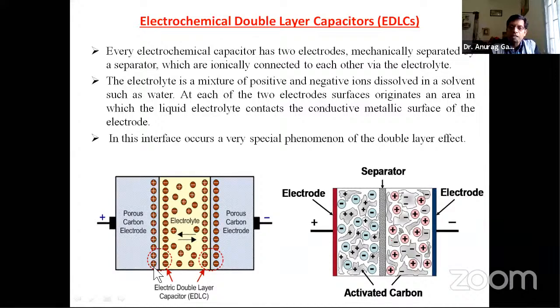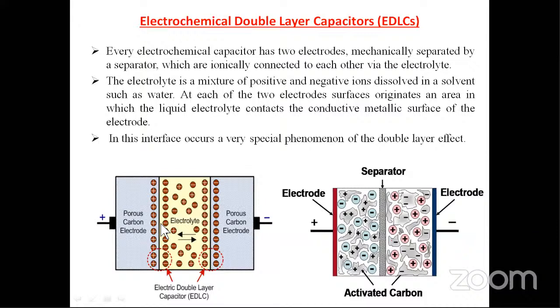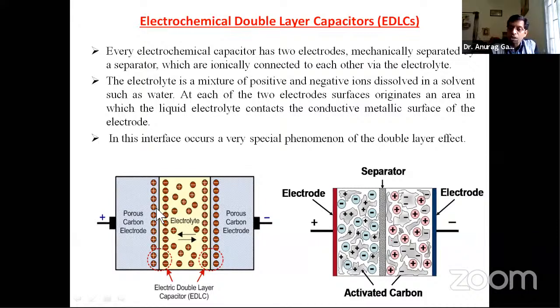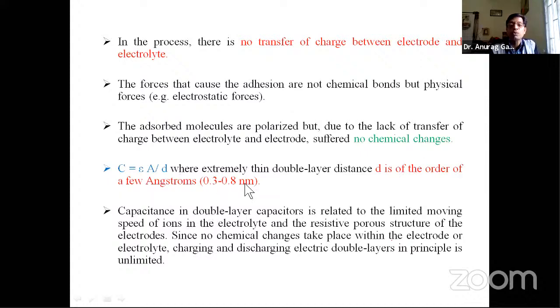So at this interface of our electrode material, the charge piles up, positive this way and negative this way. Because of that, it works as a single capacitor, and the distance between these two is at the angstrom level, as I told you. Because of that, the capacitance is very high, and another capacitor develops at the other electrode side. So we want a separator so that short circuiting can be avoided. This separator is porous in nature, so that electrolyte ions can cross from one side to the other. This is why it is called a double layer capacitor, because two layers are formed, and the distance between them is at the angstrom level, so the capacitance is very, very large. It is of the order of 0.3 to 0.8 nanometer.